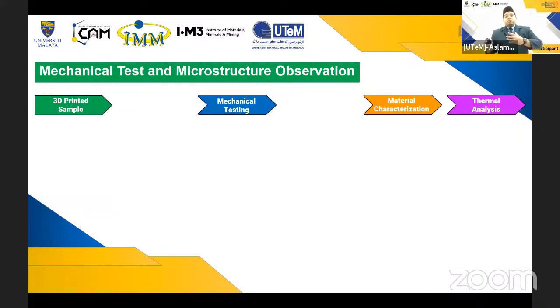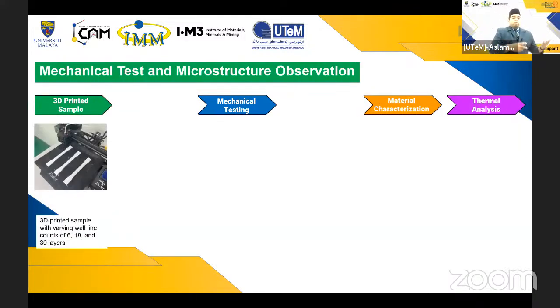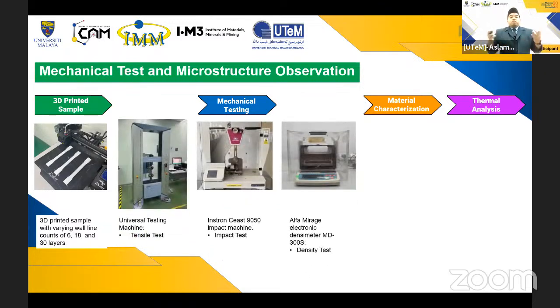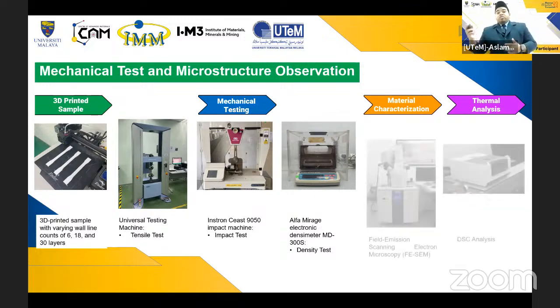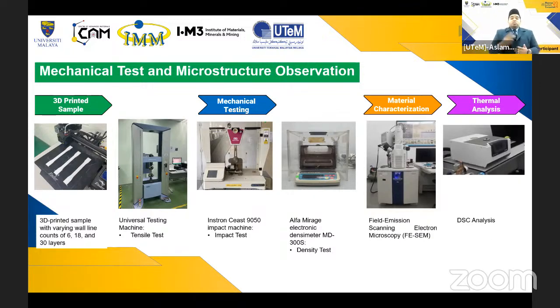So after the 3D printing of the samples with varying wall line counts of 6, 18, and 30 layers, we proceed to the mechanical tests consisting of tensile test, impact test, and density test. And we proceeded to the material characterization using field emission scanning electron microscopy, and also thermal analysis using differential scanning calorimetry.